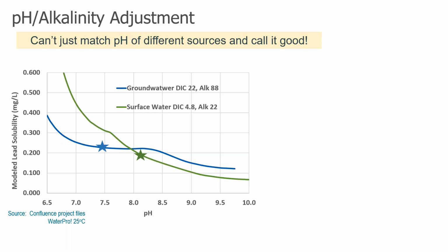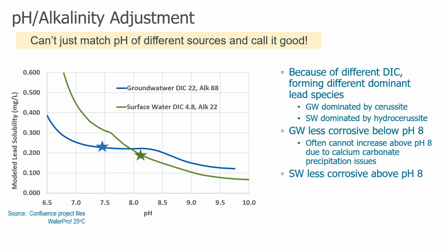Lead solubility is a function of pH, versus a groundwater with a higher DIC. And you can see the shapes of the curves are quite different. They behave differently at nearly all pH levels. And that's because of the different DIC, we're actually forming different lead species in the water. The groundwater is forming a lead mineral, in this case, that's dominated, it's called cerussite, and the surface water is forming a different mineral called hydrocerussite, and these have different solubility characteristics.